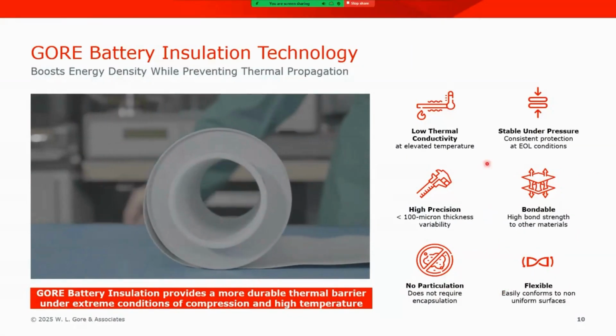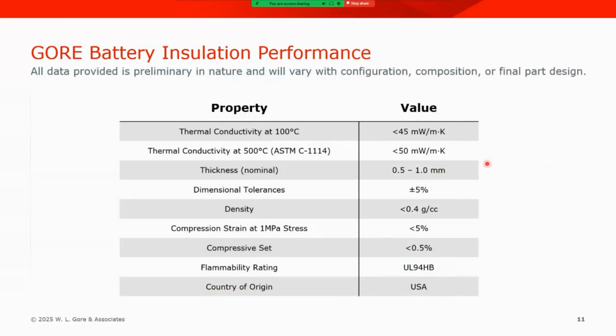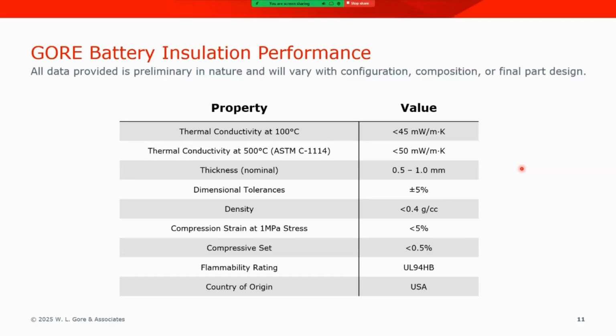So let's take a look now at the performance. Now, as this material is a technology, it's not yet commercialized. We intend to commercialize GORE battery insulation in the early part of 2026. So all of this data is still preliminary and potentially could vary with configuration composition, but this is the performance that we're expecting. Thermal conductivity at 100 degrees is less than 45 milliwatts per meter Kelvin, and that value does not change much as we go to 500 C. It rises only about 10%.